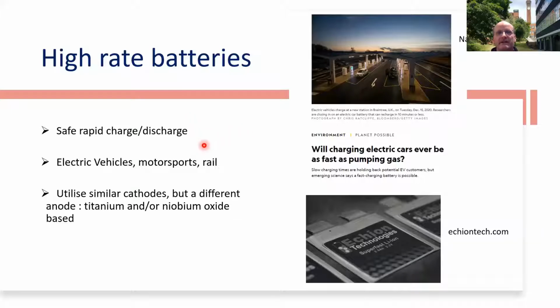So if you want really rapid charge, say charging in 6 minutes or less, which you might need particularly for rail and motorsports, then these sorts of batteries typically use similar cathode materials, so these layered lithium transition metal oxides, but rather than graphite, they'll use a titanium and or niobium oxide based material.